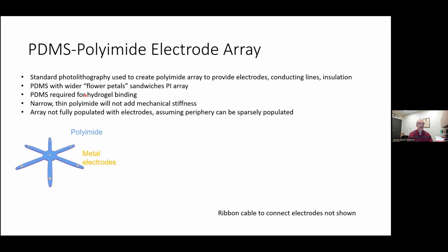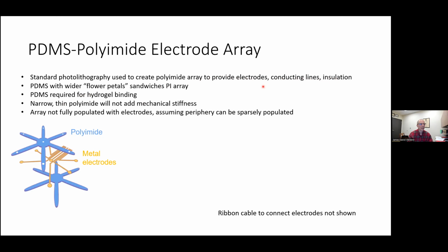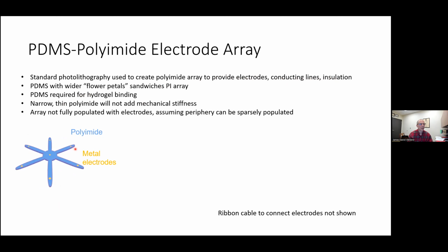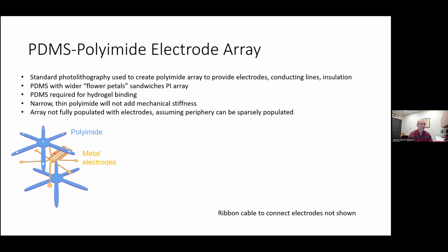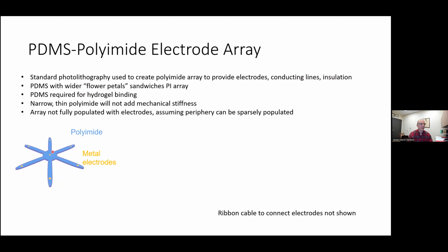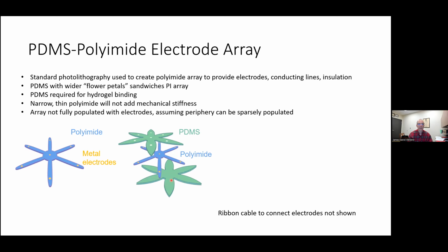We use standard photolithography to create a polyimide array. And this provides electrodes, conducting lines, and insulation. This is sort of your wires, right? We need to deliver electricity to a specific point, and the way we do that is we apply the electrical signal to these metal traces, but then we insulate it with polyimide, and we expose the polyimide at specific points. For the purposes of this demonstration device, we only included 7 electrodes, 1 in the center and 1 on each of these arms. We then sandwich this in PDMS.